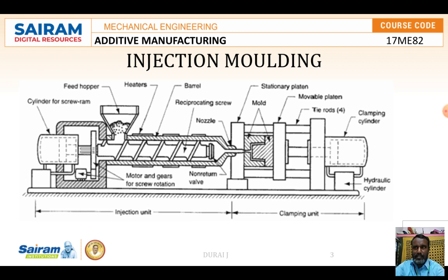By using mechanical locking devices, the mold is properly held in position as the molten plastic material is injected under high pressure. It may range from 1000 to 1500 kilograms per square centimeter. The locking device has to be very skillfully designed in order to withstand the high operating pressure.